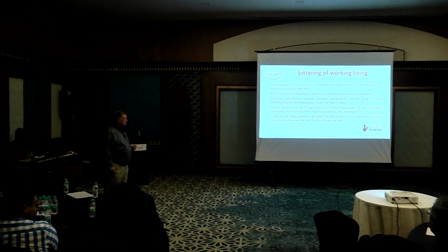Every time I go somewhere, I ask, how do you sinter your furnace? I go 100 kg and then I stop for 10 minutes. I go another 20 kg. That means nothing, and that changes over time. So if you're going to use a kg per minute type of sinter cycle, then periodically, like every 6 months, you need to drop some thermocouple wires to make sure you're still following what's approved.